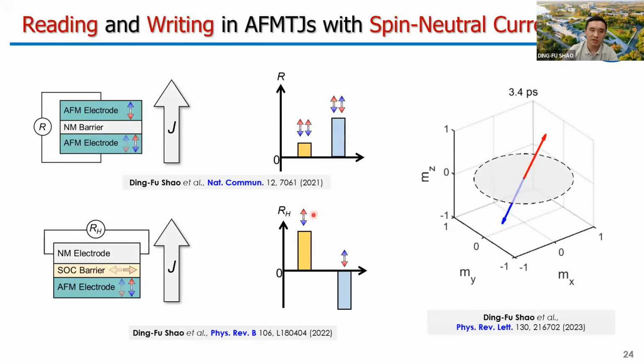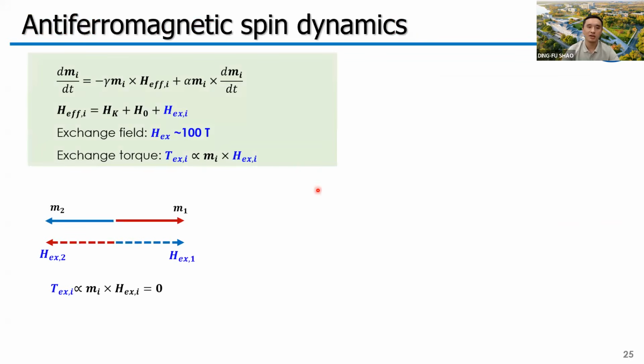So using these two examples, we prove that even with only the spin neutral currents, we can have sizable spin-dependent transport properties in an antiferromagnetic tunnel junction with a large on and off ratio. But in order to use this antiferromagnetic tunnel junction in practice, we still need to find an electric method to control the Néel vector to realize the information write-in. Let's first see the dynamics of the antiferromagnets.